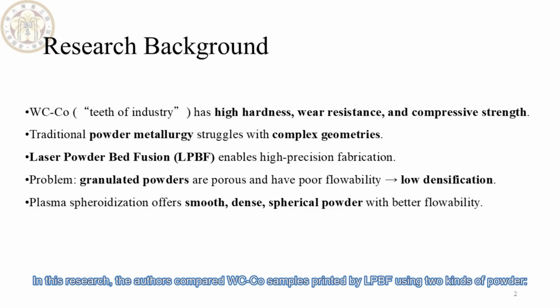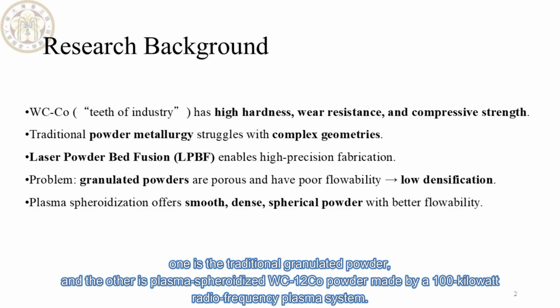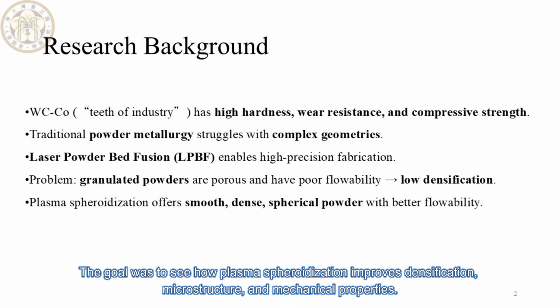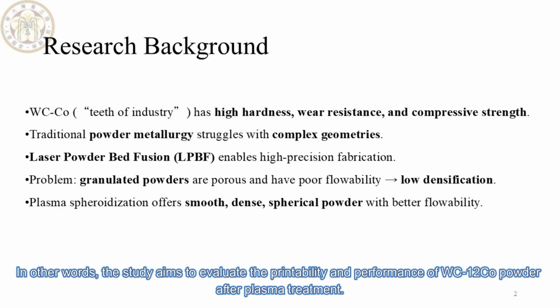In this research, the authors compared WC-Co samples printed by LPBF using two kinds of powder. One is the traditional granulated powder, and the other is plasma spheroidized WC-12Co powder made by a 100 kW radiofrequency plasma system. The goal was to see how plasma spheroidization improves densification, microstructure, and mechanical properties. In other words, the study aims to evaluate the printability and performance of WC-12Co powder after plasma treatment.